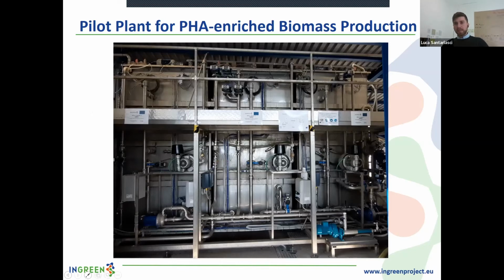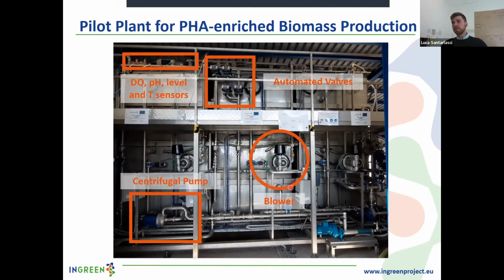The pilot unit consists of 3 sequencing batch reactors of 6 cubic meters, which you can see in the picture. Since the PHA-producing bacteria are aerobic organisms, the pilot unit has been equipped with blowers for air insufflation into the fermentation media. The main process parameters like the dissolved oxygen concentration, the pH, and the volume of each reactor can be monitored by different sensors immersed in the fermentation media. Moreover, two centrifugal pumps and many automated solenoid valves are used for the biomass transfer and the dosage of the paper mill wastewater into the reactors.